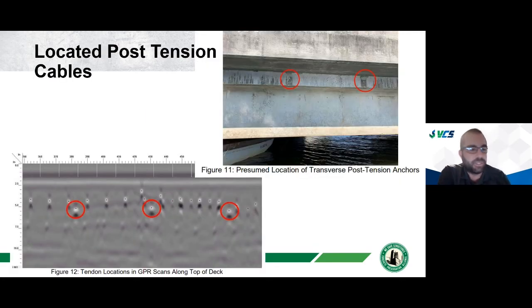Another thing that we looked at on the structure is these structures are laterally post-tensioned to keep all of the girders acting in one unit. And so some of the tendons they could see, but others, because of the pourbacks, they didn't know where they were. So we used GPR on the top of the deck to identify where the post-tension cables were. And so here's a scan from the deck. You can see the transverse reinforcement in the deck slab. And then sitting below it, circled in these red ones here, those are where the transverse post-tensioning is in the structure. So we can identify things like post-tensioning and other stuff in those.